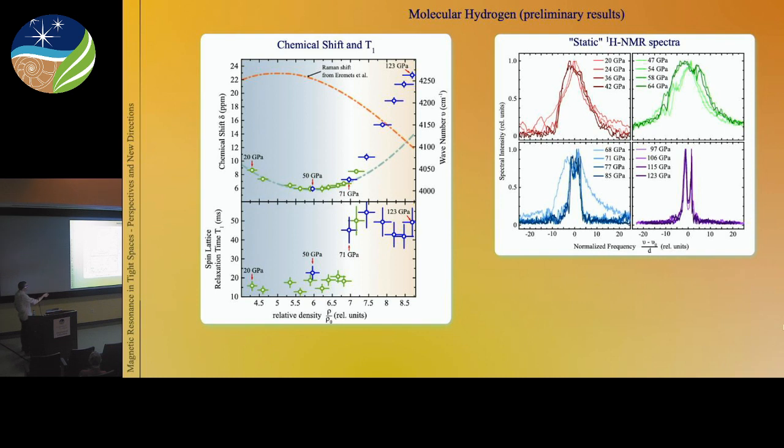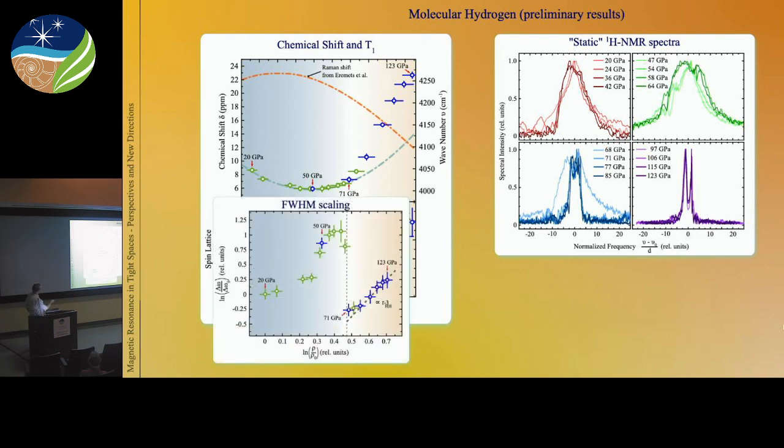And more importantly, the actual proton resonances are suddenly approaching something which kind of looks like a dipolar Pake doublet. So the big question now is what's actually happening. And in order to emphasize this transition a bit more, I plotted the relative changes again of the line width against density. And suddenly we saw that at approximately 70 GPa, we are following a 1/r³ dependence.